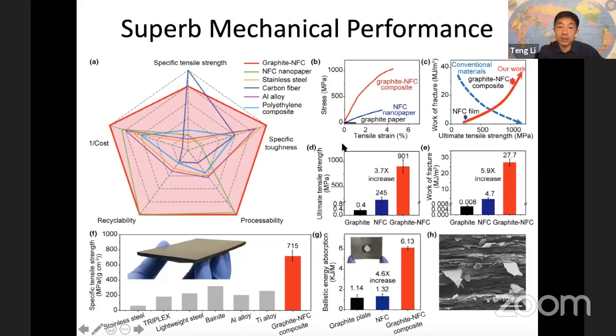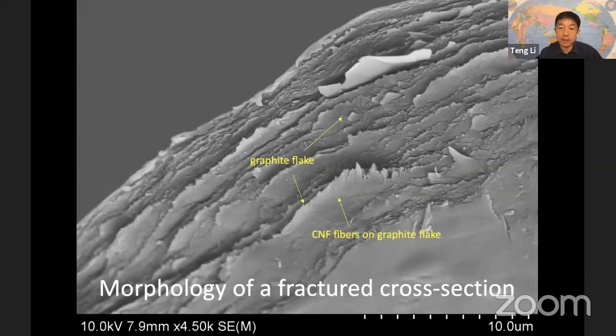And this is stress strain curve and the work of fracture and ultimate tensile strength. You see a significant increase from the pure cellulose film, several times. And in comparison with other typical metals, stainless steel, triplex, aluminum alloy, titanium alloy, the specific strength of this composite is very high. And the last, let me show you the next characterization of the fractured surface to offer you some understanding of why.